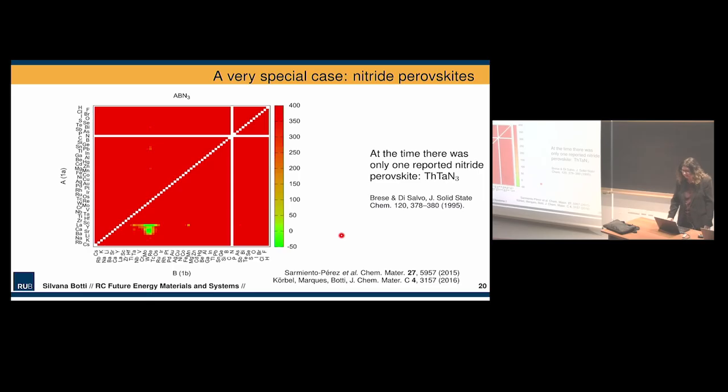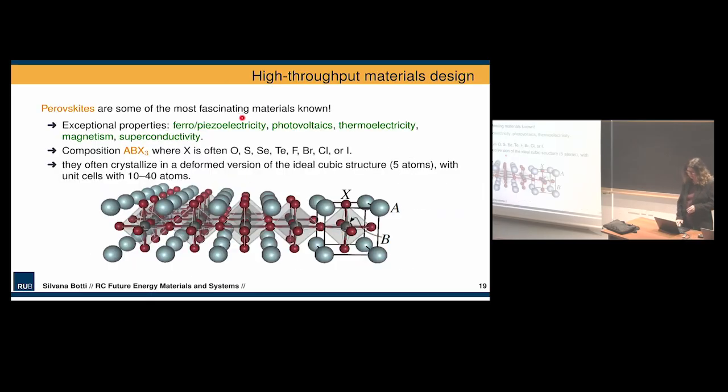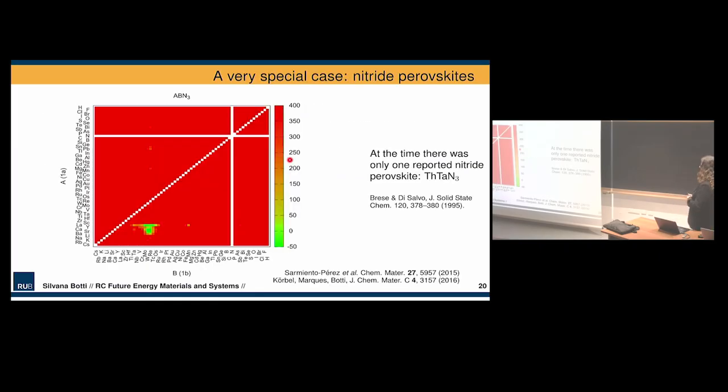And now we noticed that there were perovskites with these elements, these anions creating octahedra. There are also inverted perovskites where you have cations on the octahedra; actually, most of the stable perovskites are inverted. But we were looking at these classical perovskites and we asked ourselves, is it possible to have a nitride perovskite, so with 3 nitrogens, so A, B, and N3.